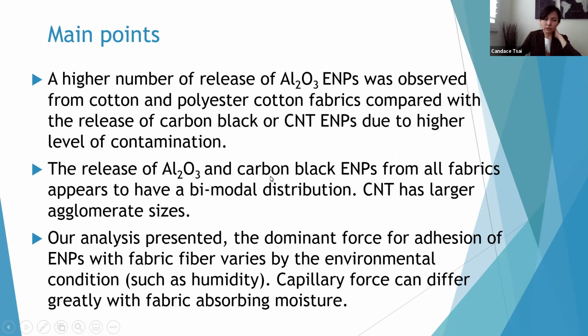We found the distribution is definitely different because they are different nanoparticles, and we found CNT has a much larger agglomerate size. The surface interaction really depends on environmental conditions, such as humidity, which plays a big role because it affects the capillary force.